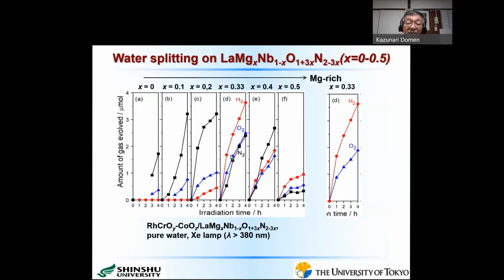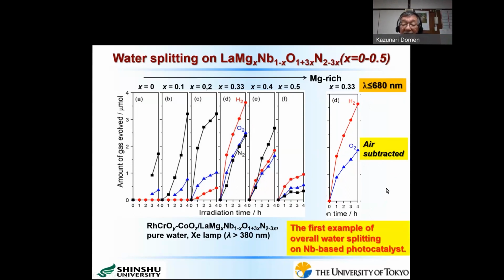As I said, this analysis contains some leakage of air. After removal of the air leakage, as you see here, both hydrogen and oxygen evolution are exactly in a 2-to-1 ratio. Also, the absorption edge of these materials still extends to about 680 nanometers. Actually, this is the first successful example of the overall water splitting reaction on a niobium-based photocatalyst using light up to 680 nanometers. So now let me summarize my talk.